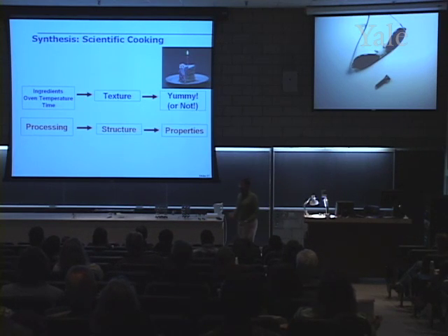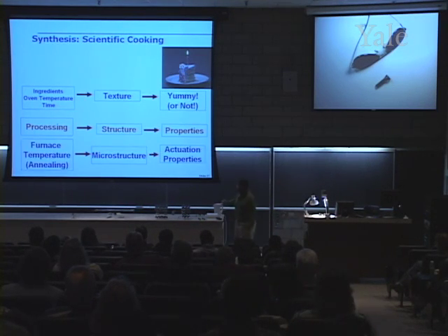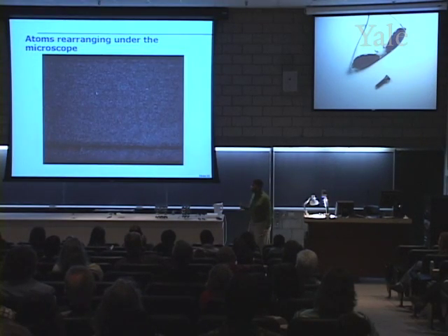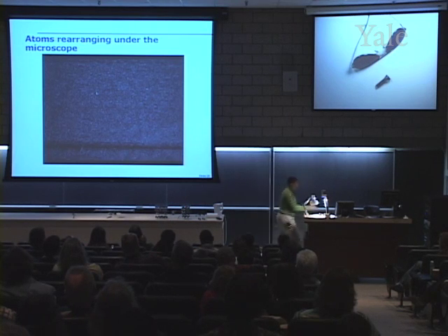Well, essentially, I guess I'm a chef in some ways because I look at nickel titanium films that are very thin. I put them into a furnace and I anneal them. That process of heating up these materials is called annealing. I look at the microstructure, that is the collection of atoms, and see how those structures look, and see how they're related to the actuation properties, that is, its ability to move. So that's essentially what I'm doing. So let's look at this process of atoms collecting and forming grains in real time.